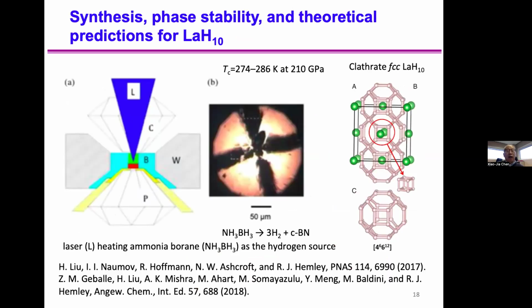Their discovery was actually based on a brilliant idea. They synthesized material using ammonia borane, NH3BH3. When you use laser heating, this will release hydrogen and also give you cubic boron nitride. Cubic boron nitride was often used to put electrical leads, holding them in gasket holes, like here, like B in this figure. That's boron nitride. When you heat this ammonia borane, it generates hydrogen.